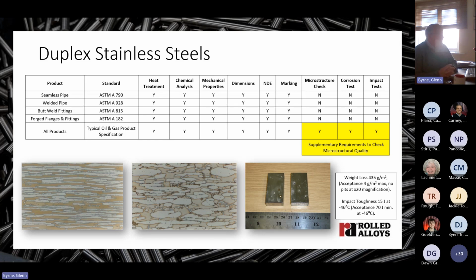But a word of caution. The occasional third phase particle is not necessarily a failure in the ISO standard, providing the material passes the other two tests. Now, we think that's a mistake. It's our view that the wrought and cast products that are to be further processed by welding should be certified as free from intermetallic phases at ×400 magnification by a competent metallographer. Because items containing small amounts of sigma can quickly contain unacceptable levels of sigma when subjected to welding.